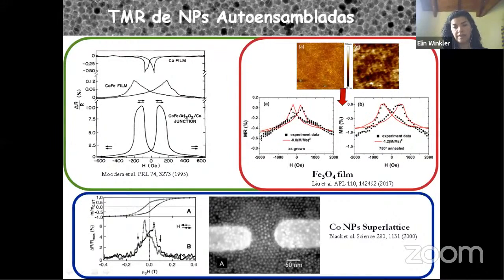A low resistance here, for example, is the magnetoresistance as a function of the field, and here we are drawing the coercivity field. And again, the maximum of the magnetoresistance is related with the coercivity of the system, which means that at high field, when all the nanoparticles or the magnetization are ordered, the system presents a low resistance state, and at the coercivity field, when the system presents disorder, the resistance of the system is larger.